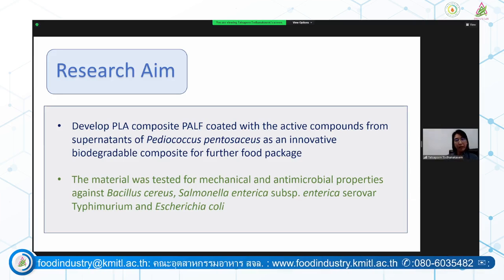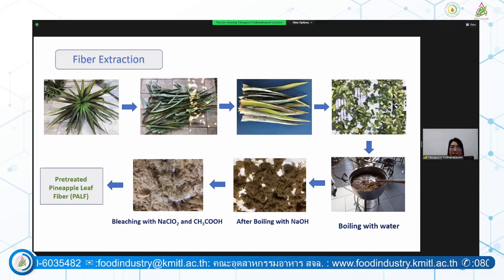So our research aim is to develop a PLA composite with pineapple leaf fiber. We want to combine pineapple leaf fiber at 10% to replace the PLA amount, and then coat it with the antimicrobial compound that we gain from the supernatant of Pediococcus pentosaceus. We isolated Pediococcus pentosaceus from fermented chicken, and we neutralize the supernatant first and use it to coat the material as an innovative biodegradable composite for further food packaging. Then we test whether this material is effective in terms of mechanical strength and antimicrobial properties against foodborne pathogens like Bacillus cereus, Salmonella Typhimurium, and E. coli.